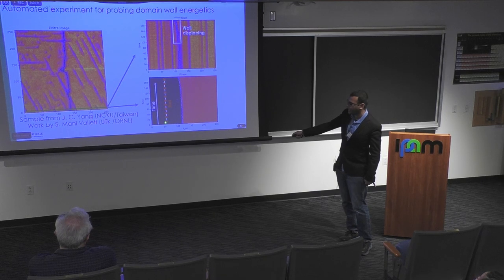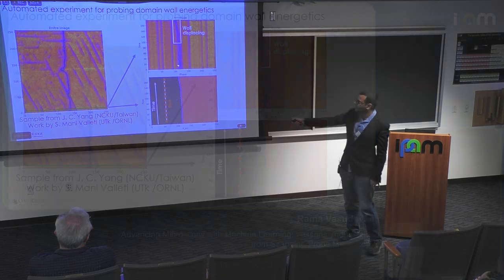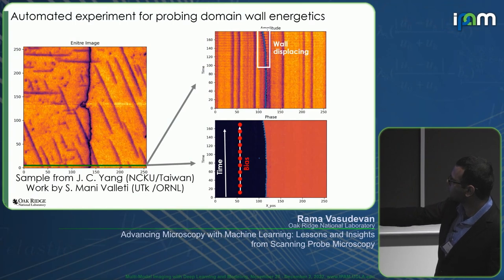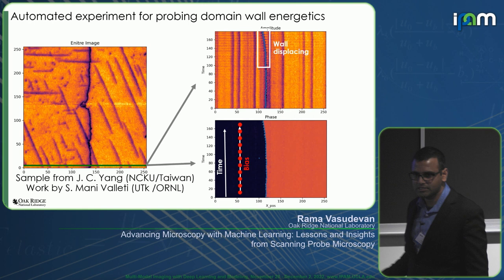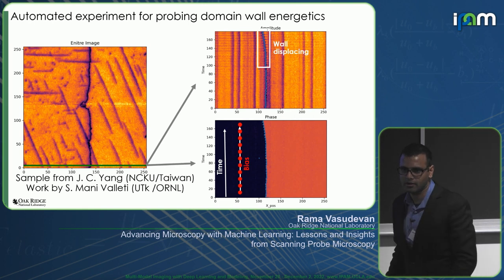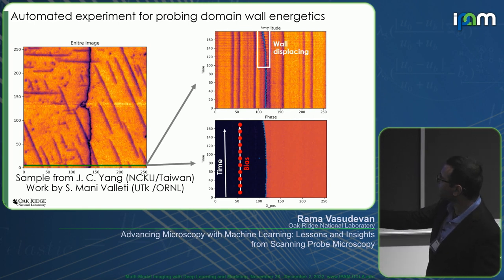for subsequent times, right? And so what we see is that initially, as you apply some voltage, nothing much happens. The wall is sort of stuck, and the reason it's stuck is because it's pinned by defects that are present within our film. After a particular voltage threshold is reached, you can start to see the wall starting to displace, right? And so we can very reliably extract the local depinning threshold by this automated experiment.